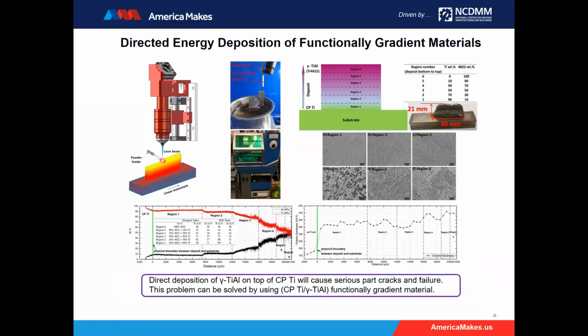And this one shows directed energy deposition of functionally gradient materials. This is done by my colleague Frank Liu. In this process, the main thing is that we want to make gradient materials because they have different properties. Some may be stronger, some other materials may be lighter, or more corrosion resistant, wear resistant. So we want the ability to vary material from one to the other. But if we just change from one material to the other, the thermal expansion may be so different that they tend to crack. And so you want to have gradient materials. You want to change gradually.